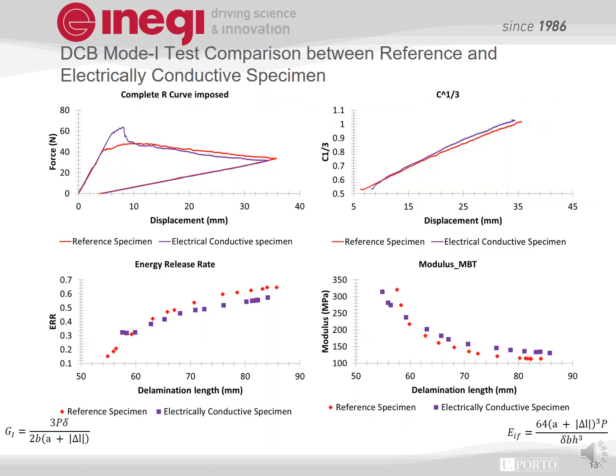This slide shows the DCB Mode 1 test comparison between reference and electrically conductive specimen. By using the modified beam theory, energy release rate, compliance, and modulus values were calculated, and then these values were compared for reference and electrically conductive test specimens. It was observed in the force versus displacement graph that electrically conductive specimens were able to absorb more energy before crack jump at the first unloading. However, both reference and electrically conductive specimens show very similar permanent deformation at the end of the second loading.